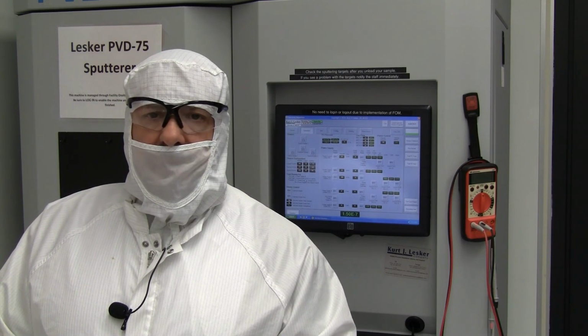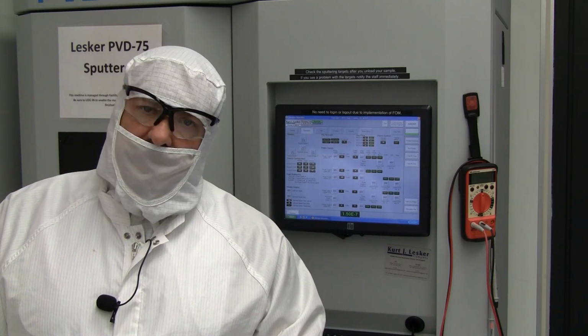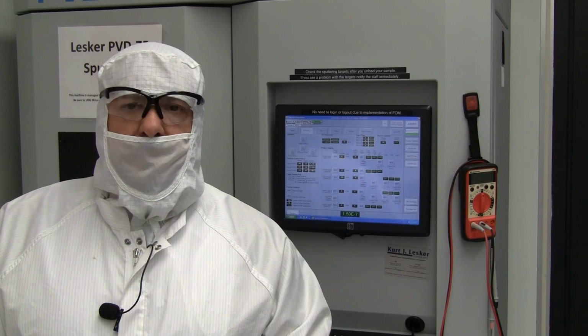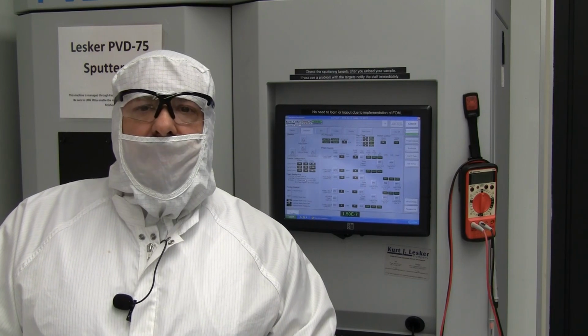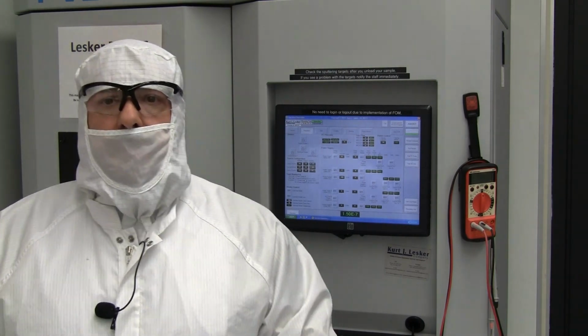So you're looking to strike a plasma. We go from about 5 millitorr on the low side up to tens of millitorr typically. Rarely will you go above 50 millitorr. The lower the pressure of the background gas, the more kinetic energy your ions have, although there are fewer of them, and also the more kinetic energy your neutrals have upon arriving to the substrate. Why does that matter? Because the more kinetic energy your neutrals have, the more perfect film you make.